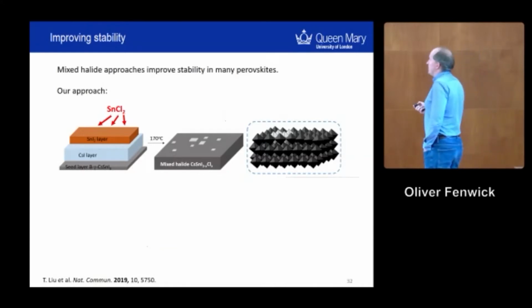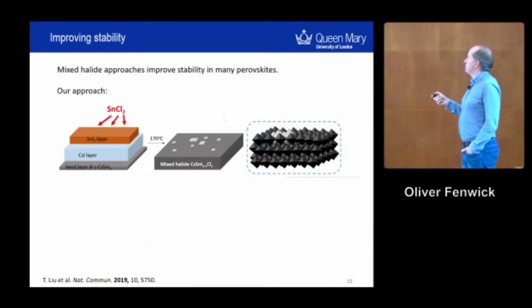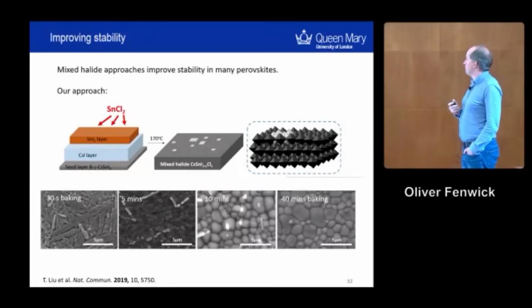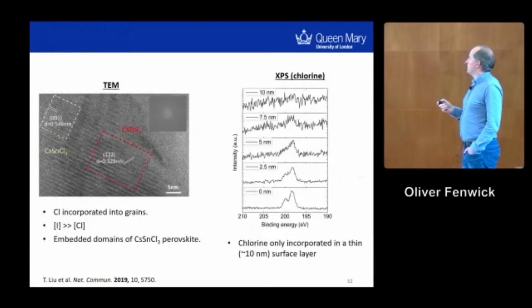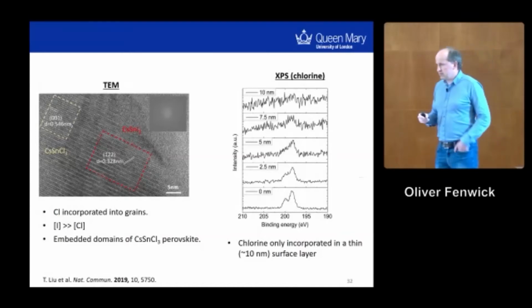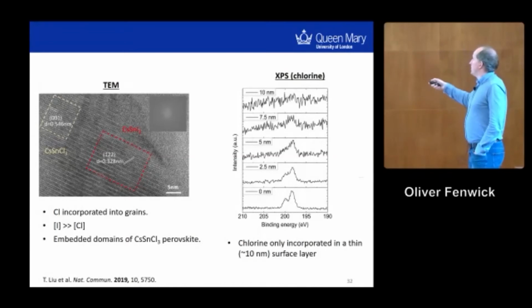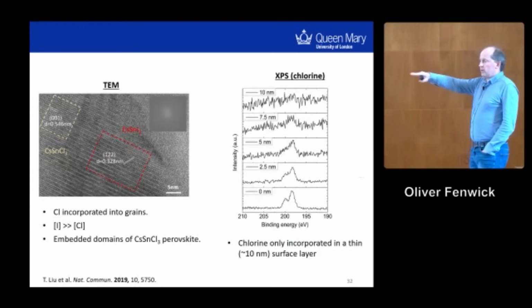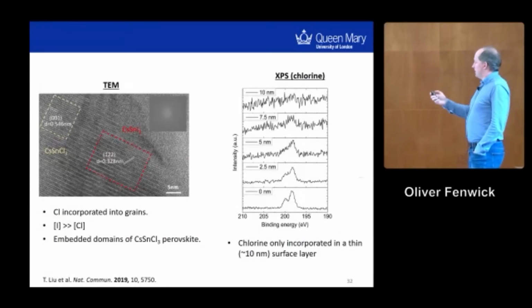We wanted to improve the stability though, and so we put a bit of tin chloride on top to try and go for a mixed halide approach that is known to increase the stability of the materials. Once it's on top, we bake it to try and get the chloride to incorporate into the perovskite structure, which it does, although we do see tin chloride domains on the surface, so it doesn't mix entirely with the iodide. And it only stays near the surface, only in the top few nanometers we find, which is also where we find the tin oxidation occurring.